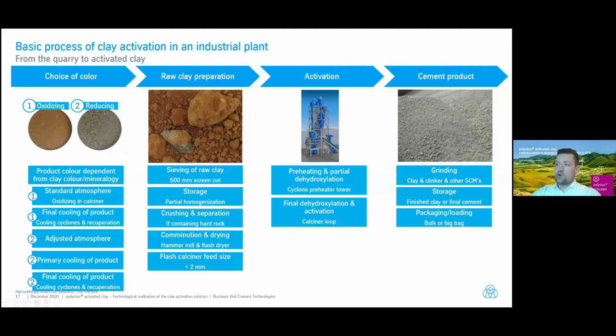So the last point then is the cement production. So here there are principally two ways. One way would be to have an intergrinding together with clinker, limestone, gypsum. And the other way would be to have a separate grinding. So just grind activated clay and then afterwards mix it with the cement. And this might be of advantage later because you are pretty well able to steer the quality of the cement when applying a separate grinding.